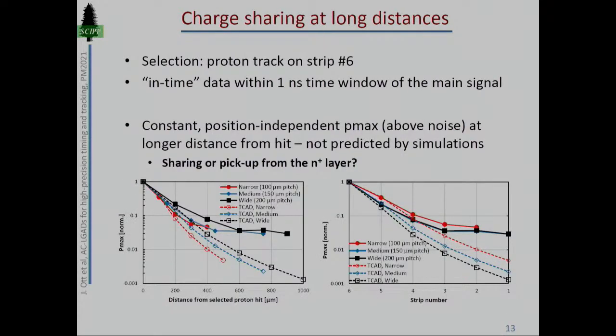We've also observed that at long distances, we still see some kind of signal component that's well above the noise. We quantified this by having a track on a specific strip and then looking at strips further and further away. This does scale to some degree with the distance for all the different strip types investigated, but further away, after the second neighboring strip on each side, this seems to level out. This is not entirely understood yet, so the TCAD simulations are not able to reproduce this. It's going to be interesting to investigate this further and see just how much the N+ layer affects this.